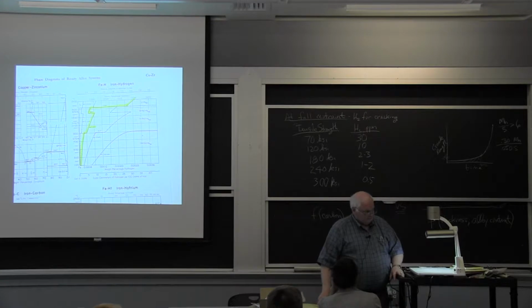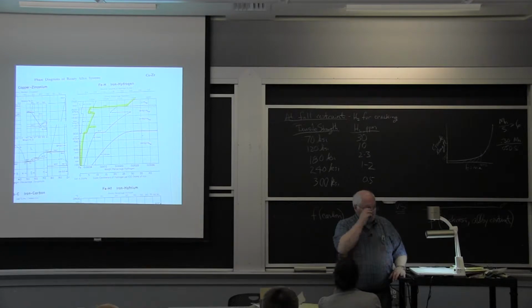Yes? Does it change the microstructure of the steel? You could get reheat cracking that I talked about before, so that when you come down from the stress relief, you have cracks to go along with your stress relief. But if you control the composition of the steel, and we know how to do that now, you don't get reheat cracking. It actually usually improves properties if you do it properly. You certainly usually improve toughness, and you improve fatigue resistance. But it's a little pricey to heat it up like that.